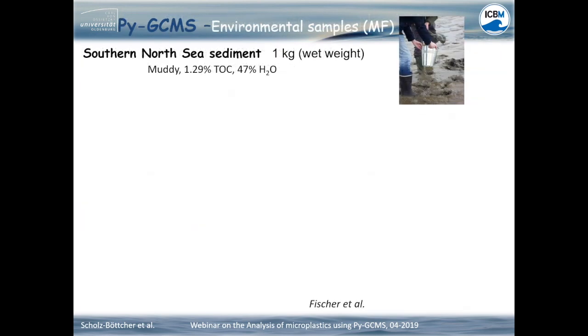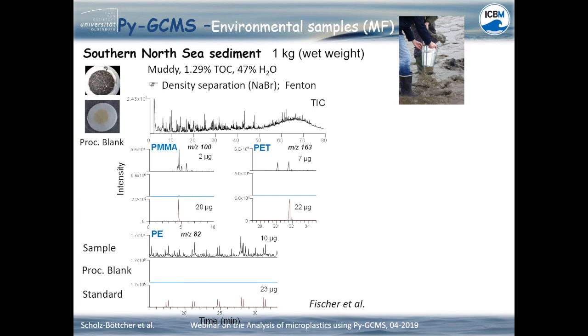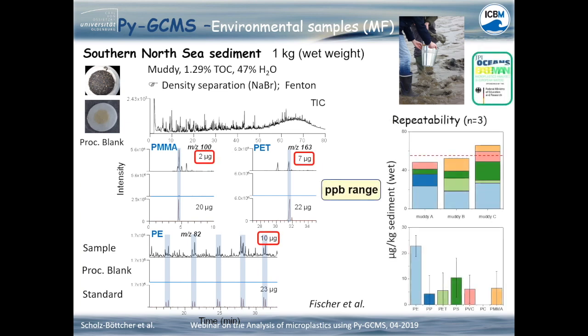The next example shows the results for a typical muddy Wadden Sea sediment analyzed with microfurnace pyrolysis. The total ion chromatogram is shown in contrast to selected indicator ions of PMMA, PET, and polyethylene. In total, 6 different polymers were analyzed. The sediment was analyzed as triplicate, and the differences in abundance represent the variability in natural particle distribution, which seems to be much less for polyethylene compared to the other polymers. All in all, the concentrations found in these sediments are in ppb range.